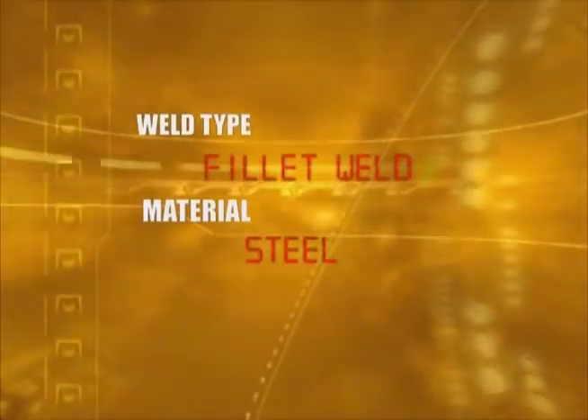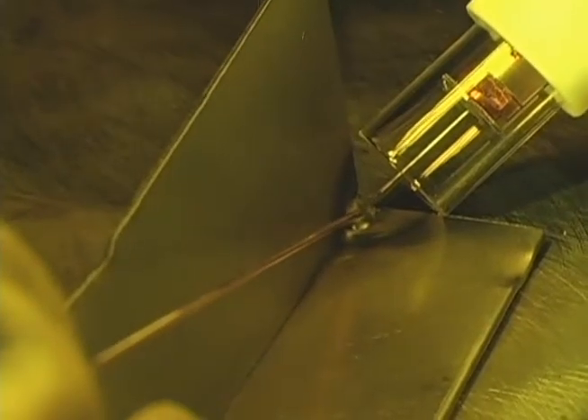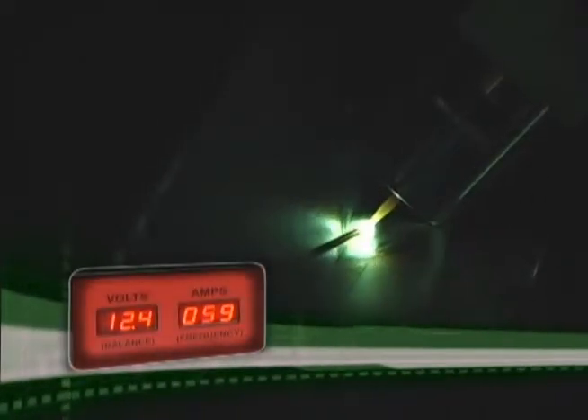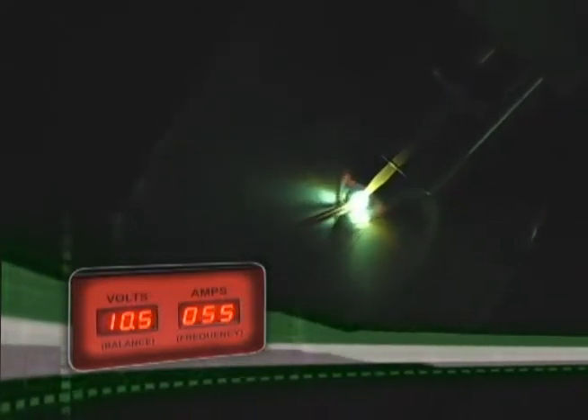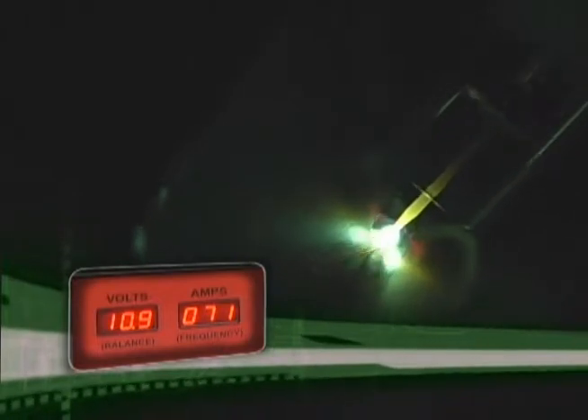Fillet weld. The fillet weld is 2 panels at 90-degree angles. This is the hardest weld because it is very easy to melt away the edge of the upper panel. The heat should be concentrated on the lower panel using the molten puddle to wick up into the upper panel, similar to a butt weld.